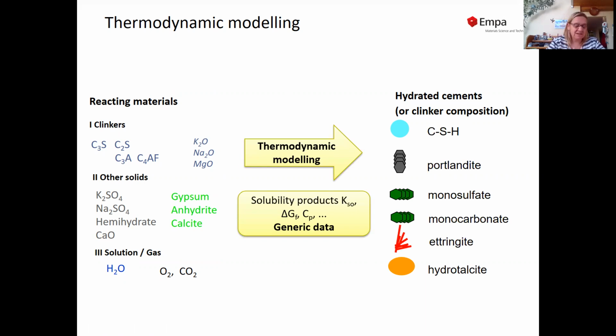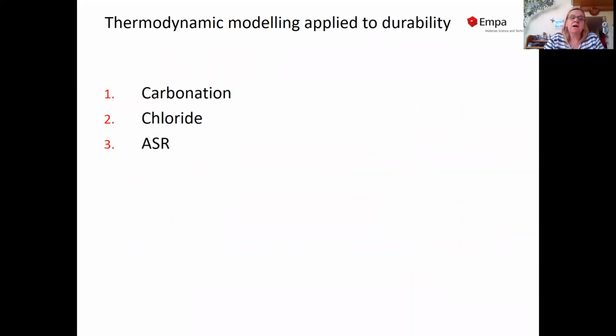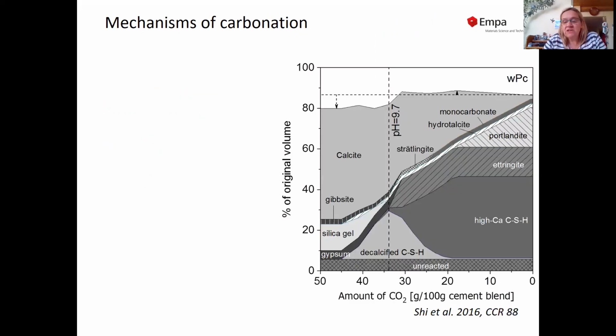And we can apply the same thing also to durability issues, and all the predictions are based on thermodynamic data, which are basically generic data, which means we can measure the solubility of gypsum in a beaker of water, and the same solubility we can also apply to our cementitious systems. I want to speak about carbonation, chloride, and alkali-silica reaction product, and we might just start with carbonation.